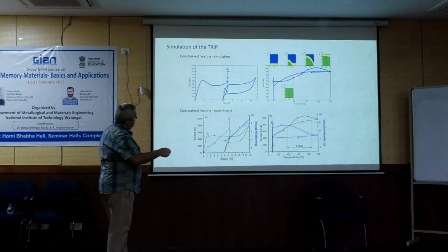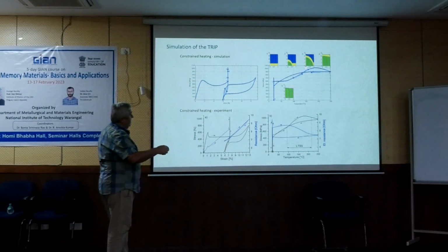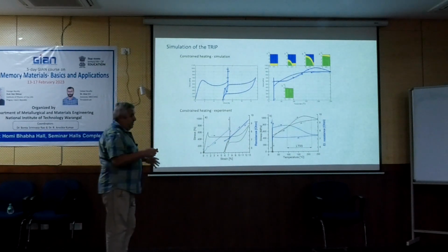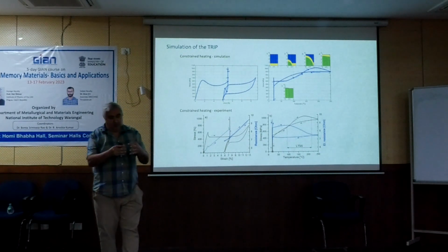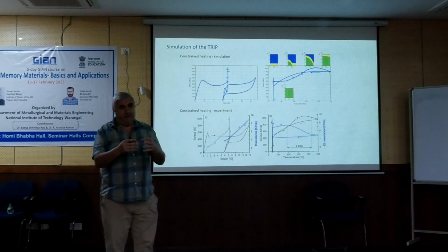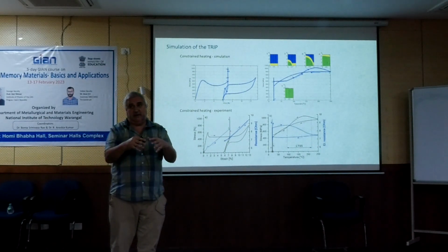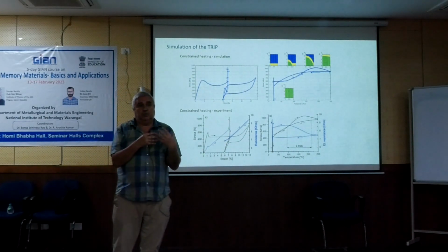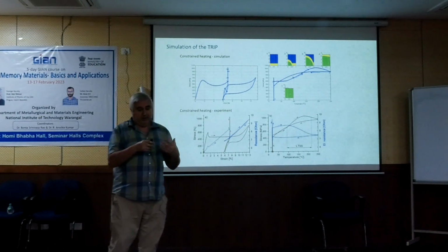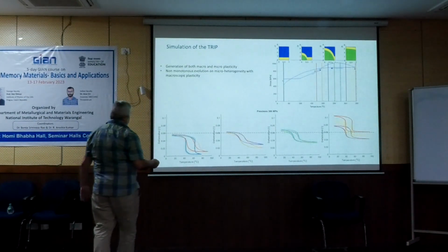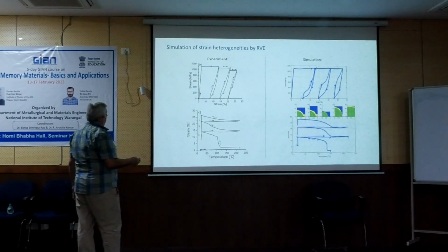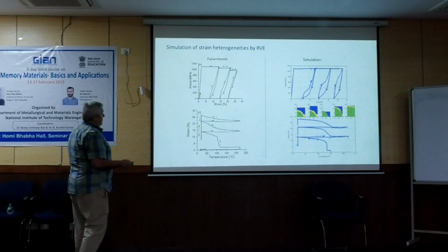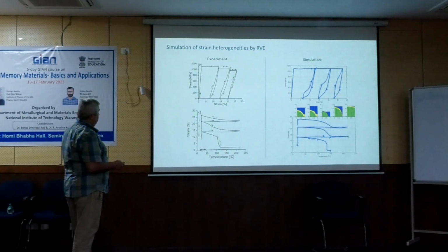When you are loading this wire, the martensite is transforming to the austenite, but at the same time it is changing the microstructure. And indeed, at this maximum, the austenitic microstructure of the wire is completely different, with many introduced defects inside, and we are attempting somehow to introduce this into the model. I will come back to it after explaining the experimental evidence for something like that.